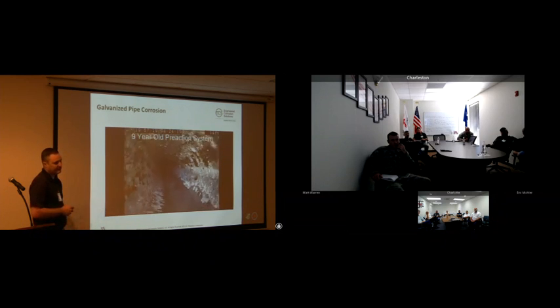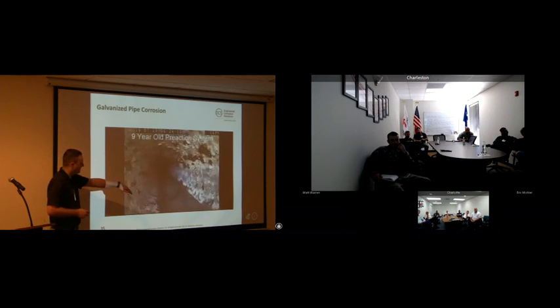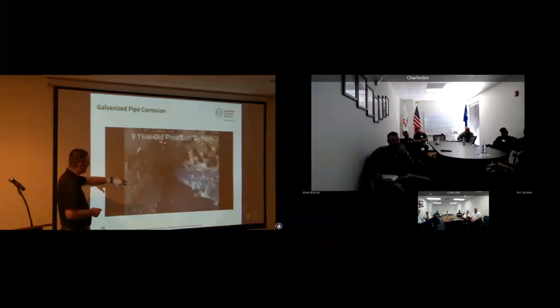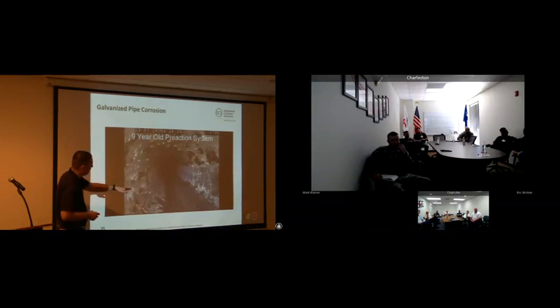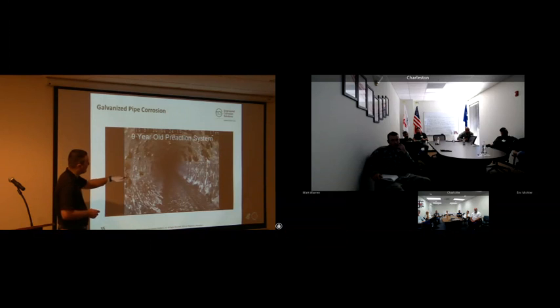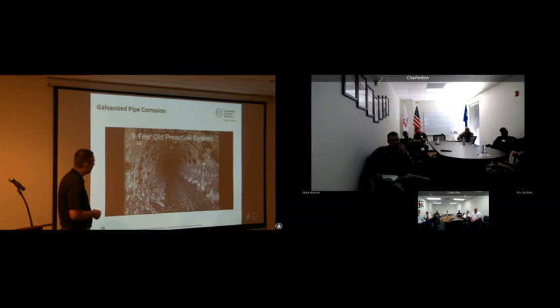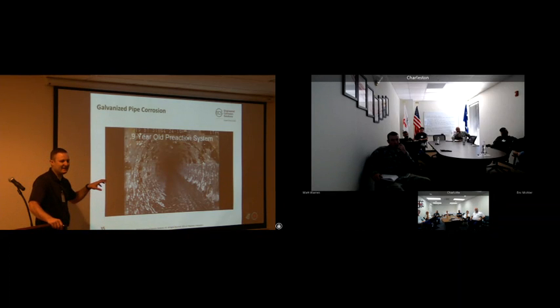So that is much worse than that 9-year-old protection system we looked at, or 10-year-old black pipe system we looked at. The top of the pipes at the bottom, we didn't have a self-leveling camera at this point, but you can see there's multiple air-water interface lines in here. So at different given times, there was different amounts of water in it, and you can tell at that first one near the bottom where it's almost all white, that water level didn't sit in there for very long, probably only 60 days or so.